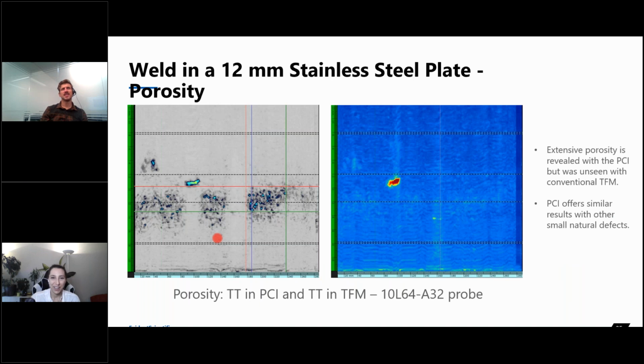Thank you. So this one is an interesting one, because that's the sample that we've had for quite a while now that we've been using for a lot of our tests in our lab. And that's a 12 millimeter stainless steel plate that had porosity in it. We knew it had porosity, but we thought there was one single pore. We tested it with UT, we tested it with PAUT, we tested it with conventional TFM, which this blue image comes from. We can see that large pore, or that single pore there.